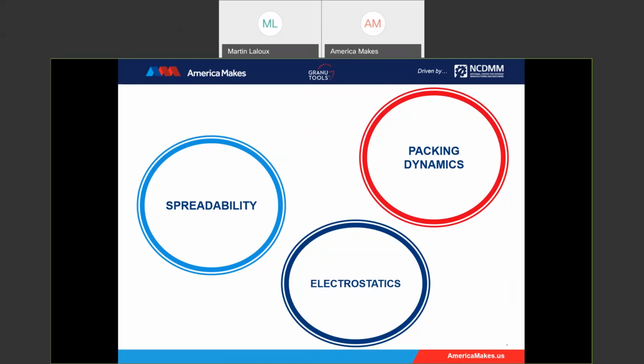The second parameter is the packing dynamic. This is a key parameter also because a powder with a fast packing means a part with low porosity. And finally, the electrostatic will be studied also. This is the ability of a powder to create electrostatic charge during a flow. The presence of electrostatic charge in the powder induces cohesive forces leading to the formation of agglomerates.